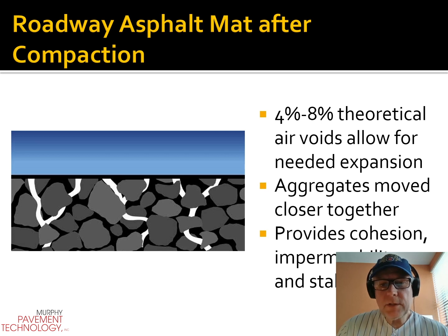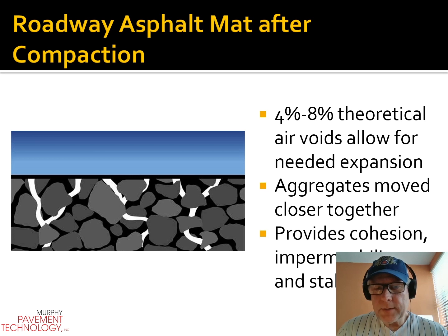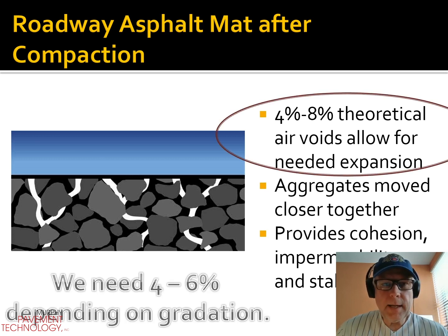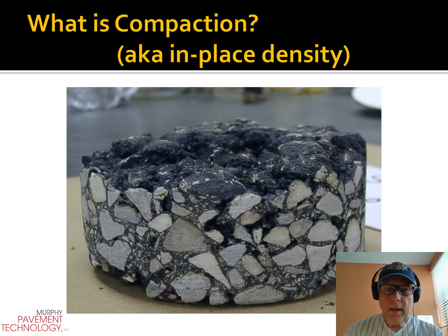Air voids are going to be reduced, and we don't want them to be, as we call it, interconnected. They do provide for cohesion, keeping the product together, and it makes the asphalt what we call impermeable. If you have low density when you install asphalt, then you may end up with moisture stripping your asphalt apart. This is a core that's actually turned upside down. Water traveled through 3 inches of asphalt and started to scour the asphalt and pull it apart.